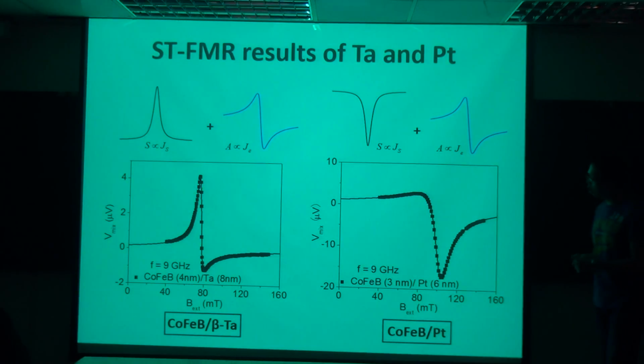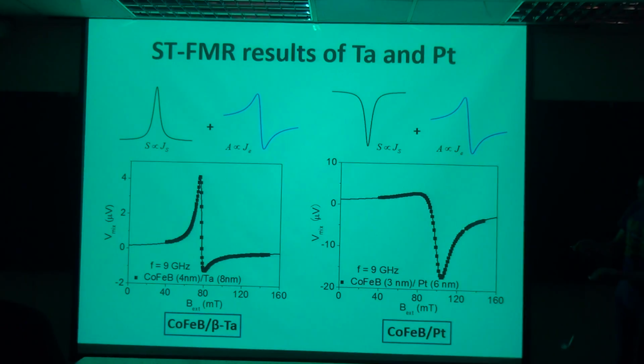And that's what we got from cobalt-iron tantalum bilayer system, and also cobalt-iron platinum bilayer system. So you can see the anti-symmetric parts have the same sign. So the blue ones are the same for these two data, which means that the Ørsted fields are the same, which is as we expected. But the symmetric part, which is coming from the spin Hall effect, they have opposite signs. And at least at that time, the spin Hall scenario is the only scenario that we think is correct and can explain the data we observed.